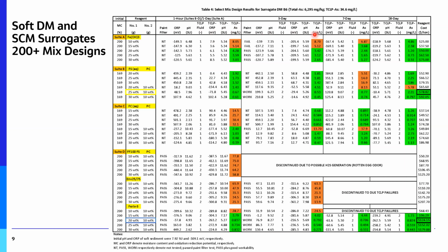We tracked it at 1 hour, 3 days, 7 days, 28 days, and then I'm showing you the reagent unit cost in the rightmost column. So let's take a look at a couple of these. So here, we're adding aqueous ferric sulfate, which seems odd. Why would I add a liquid to immobilize a liquid? But in fact, all the iron is in solution. Dry reagents typically foul. So delivering arsenic and having iron in solution to react with that soluble arsenic is important, right? So in high water content stabilization challenges, we're often adding our reagents in aqueous form to enable the immobilization reaction to occur, precipitation, sequestration, etc.